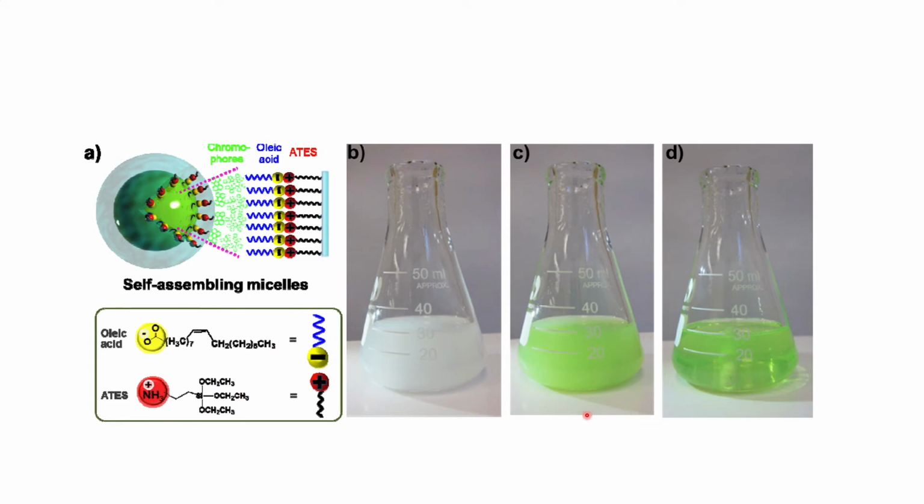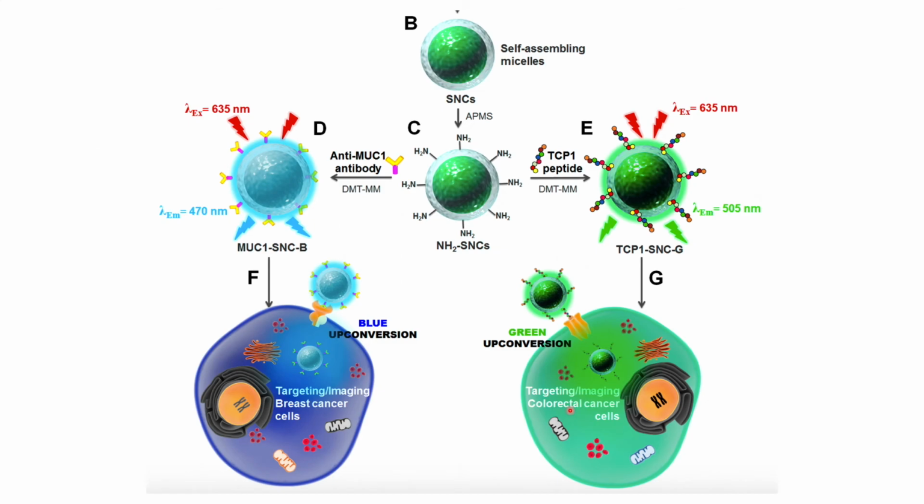These micelles were then further reacted with tetraethyl orthosilicate to form silica shells. The surfaces of these nanocapsules were then functionalized with amino groups by adding 3-aminopropyl trimethoxysilane. This allows for the covalent attachment of cancer-specific bioprobes, such as antibodies or peptide sequences.